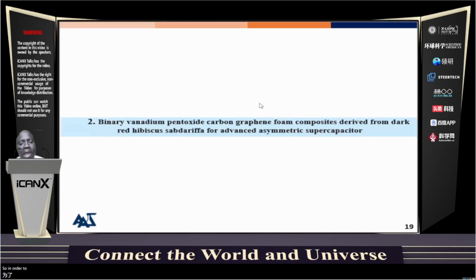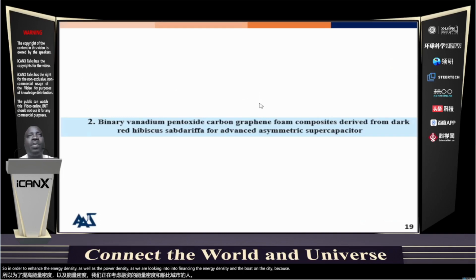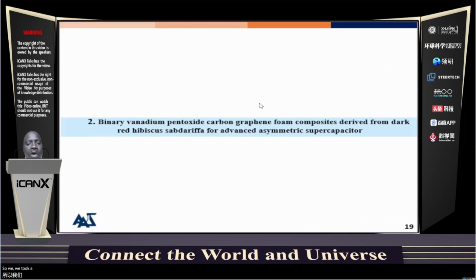So we are looking into balancing the energy density and the power density, because supercapacitors, as I said earlier, have high power density, but they are really lacking in energy density. We need to enhance the energy density without compromising the power density. So we are working on balancing. So we took graphene foam and imbibed it into the material that I just presented, to see what could be the effect of this graphene foam.